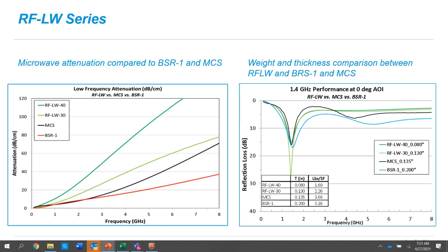The other advantage here is a tuned material at 1.4 gigahertz, very low frequency, GPS frequency. You can see our standard BSR1 would be 200 thou thick. When we go to RFLW 40, you're at 80 thou thick, so over 50% thickness reduction. So that's some of the advantage of this material. So low frequency, corrosion resistant, a new solution.